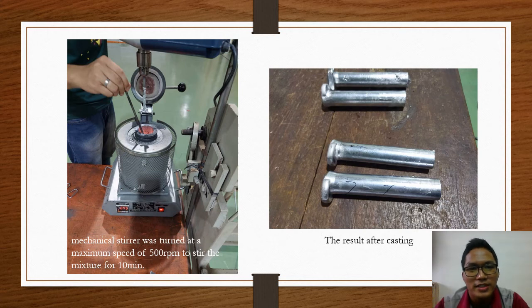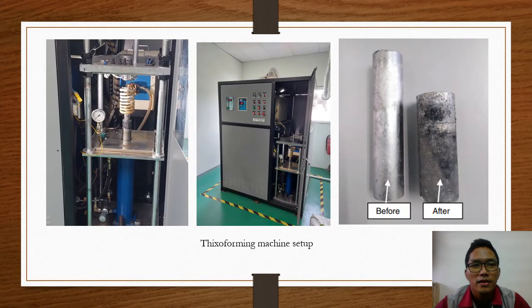Multi-wall carbon nanotubes powder and magnesium flakes were mixed together and wrapped with aluminum foil before being immersed into the A356 alloy by using a plunger. The content of multi-wall carbon nanotubes involved 0.5 weight percentage and 1.0 weight percentage respectively, and 0.5 weight percentage and 0.75 weight percentage of magnesium. The mechanical stirrer was turned at a maximum speed of 500 rpm to stir the mixture for 10 minutes. The specimen was continued with the thixoforming process.